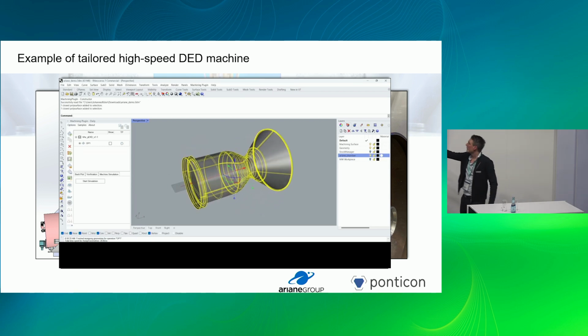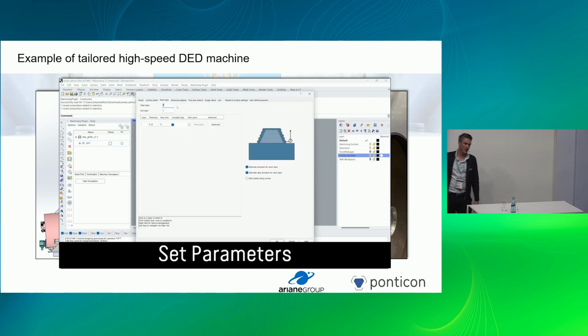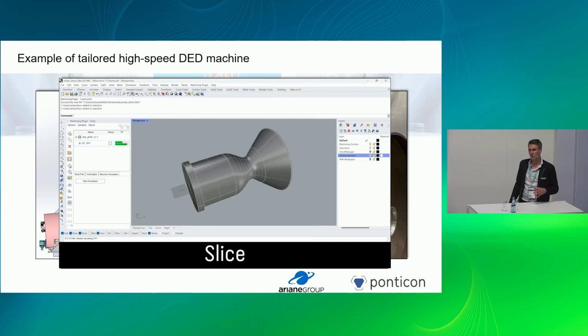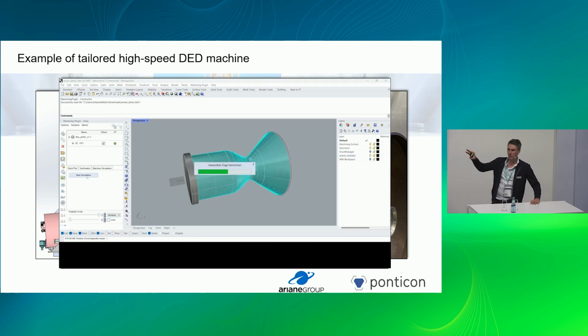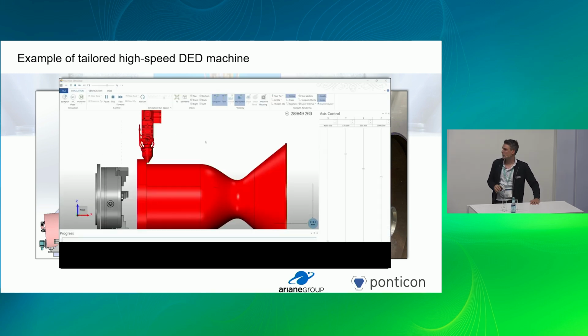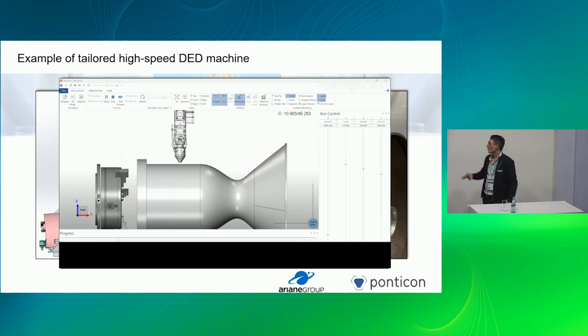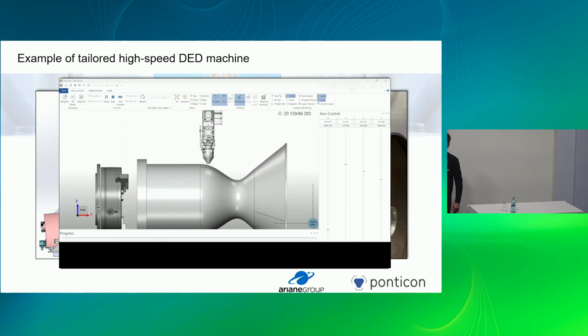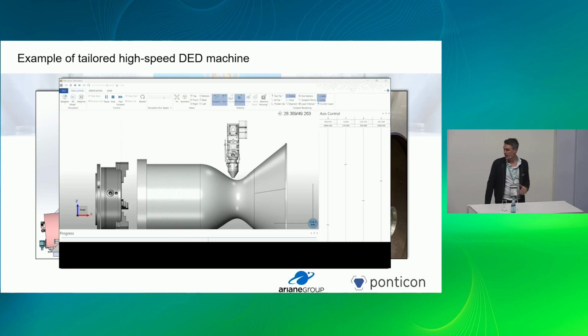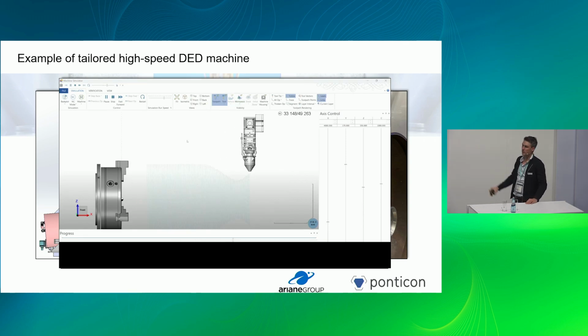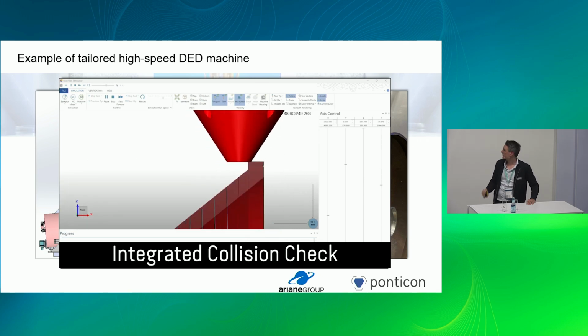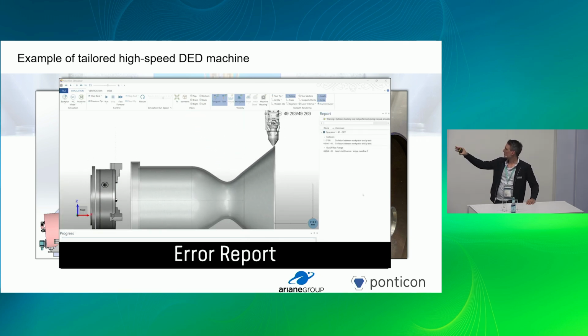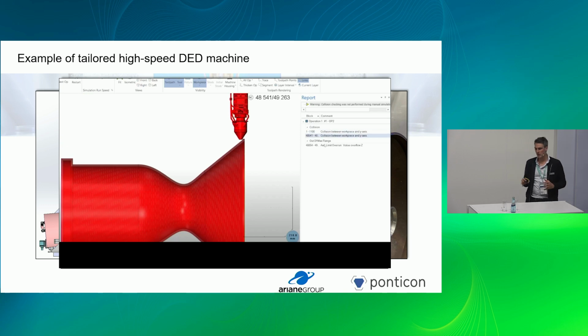Okay, so what we see here is a benchmark part, a thrust chamber that was provided to us by Ariane Group to find out how well the process performs. This is the entire workflow from the toolpath planning all the way to the actual machine and the process. With this approach, we were trying to find out what kind of angle we could still tackle without tilting the head. The one on the left still works; the 45 degrees is obviously critical, so you would have to tilt the head. What's nice about this is you have collision detection, so it's really all there to make sure you have an efficient setup process.